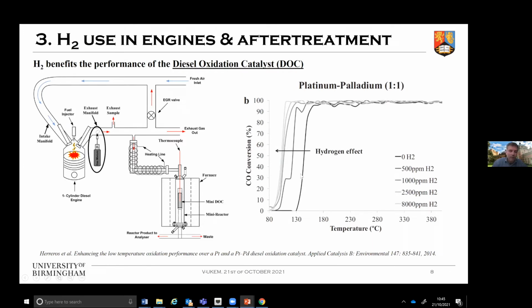Then by doing that, we observed that when we did the catalyst light off without hydrogen, the catalyst started to be active around 130 degrees. And then when we were injecting this upstream hydrogen, we were able to make the catalyst active at lower temperatures. Something interesting here was that small hydrogen additions were able to enhance catalyst activity, but as we kept increasing the hydrogen concentration, the advantages were not so great. So it seems that we have some limitation here. And then doing further calculation afterwards, we understood that this is a combination of both: a thermal effect, where hydrogen is burned and this locally heats up the catalyst active site, as well as a chemical effect of hydrogen or hydrogen-derived species in the oxidation reaction.